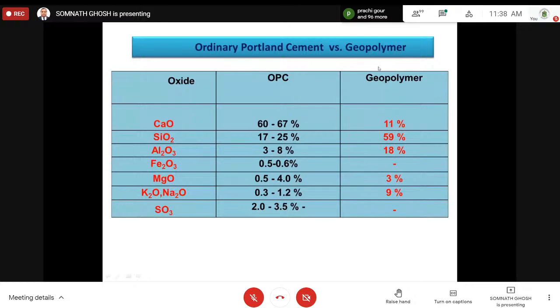Now, why am I saying geopolymer? Because here I'm discussing fly ash plus alkali and silicate. It will give you a binder which is polymeric in nature. And fly ash means it is from coal, geo means mitti. That's why we call it geopolymer. But nowadays, people are not really calling it geopolymer. Rather, they are using the term alkali activated composite, because it's a general term. If you use slag, then the polymeric reaction is not taking place. I'll come to that. Of course, today it is not possible because we don't have time.